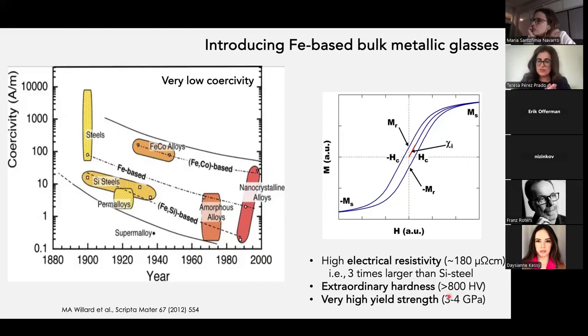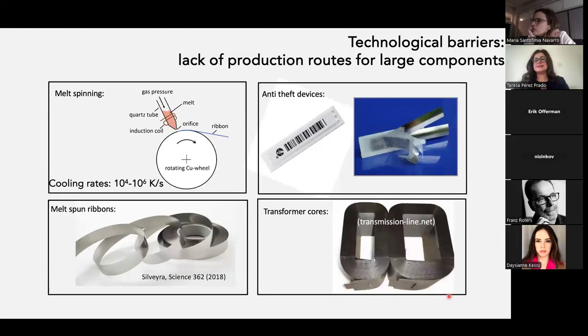So what is the problem then? If we have such good properties, how come we are not using these materials? The reason is that there are very high technological barriers to produce bulk components, especially of complex geometry, with these materials. In order to stabilize this amorphous phase, which is what conveys these nice properties, we need to use very fast cooling rates. Here you have the range between 10 to the 4 and 10 to the 6 Kelvin per second. Of course, for most manufacturing methods that we have available, this is not possible. There are only a few manufacturing methods that can do that, and the most commonly used here is melt spinning.